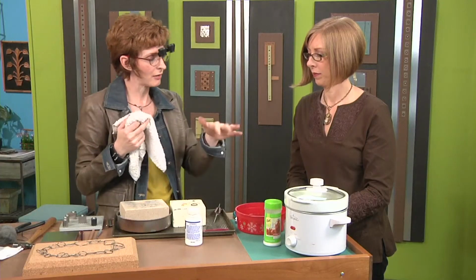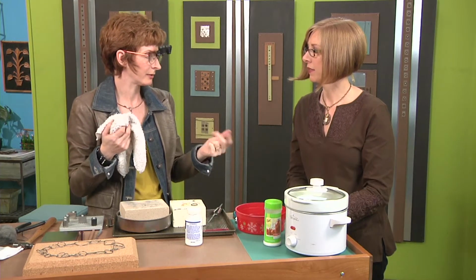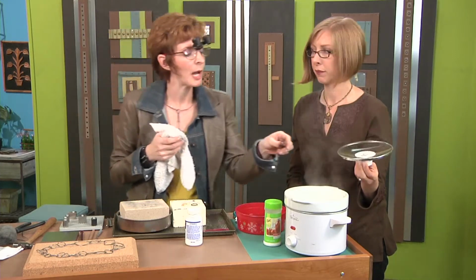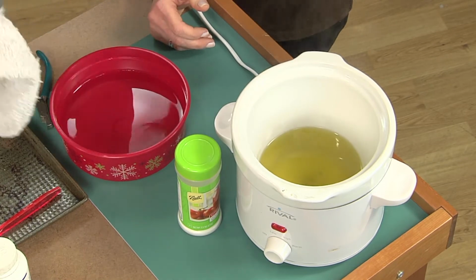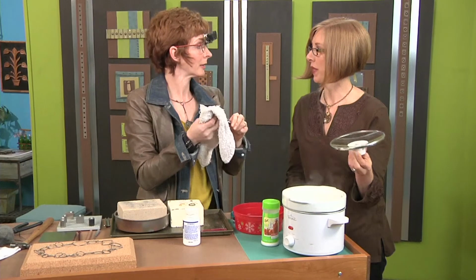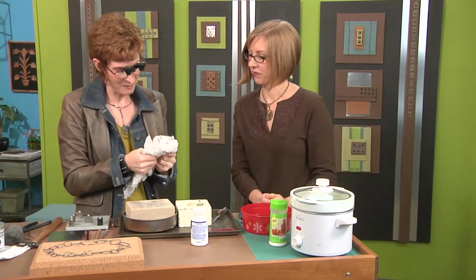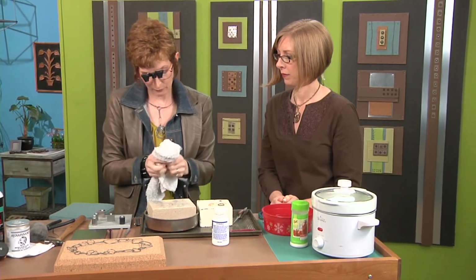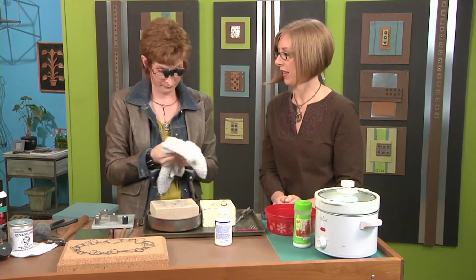What I was going to say is that generally it's a no-no to use steel tongs with it, but we have totally dedicated steel pickle pots. If you were using other metals, it could cause tarnishing. Actually, what happens is that the copper plates right onto all your other metals. So if you have a lovely sterling silver necklace, it becomes copper plated, which is okay if that's what you want, but probably not. Okay, I have my little shop towel here, and because we don't have a whole lot of time, this won't look exactly beautiful, and we're going to pretend that we have two really good solders, right, Katie? Yes, sounds good.